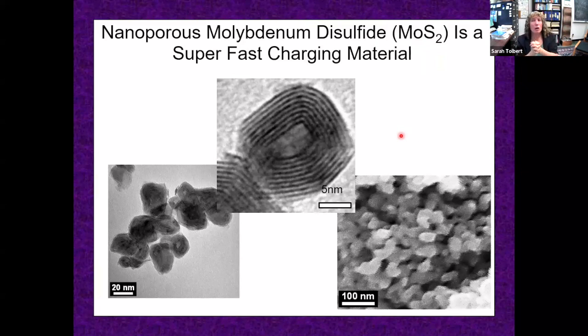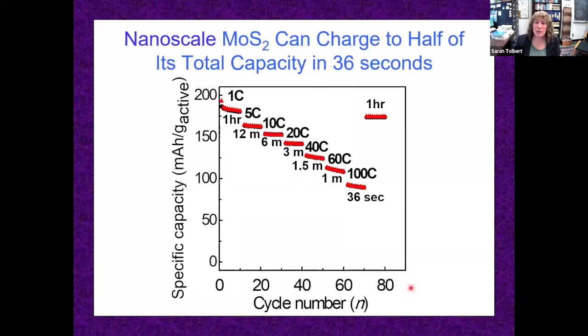The problem is it's hard to make moly sulfide small because when you start to make it, it grows big sheets. So in this work, what we did is we made nanocrystals of moly oxide and then converted them to the sulfide. And the layers of the moly sulfide just sort of stuffed themselves into our nanocrystal any way they could. And then we assembled those into porous networks. This material is blazingly fast.